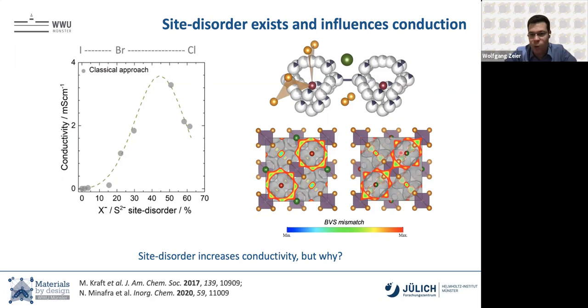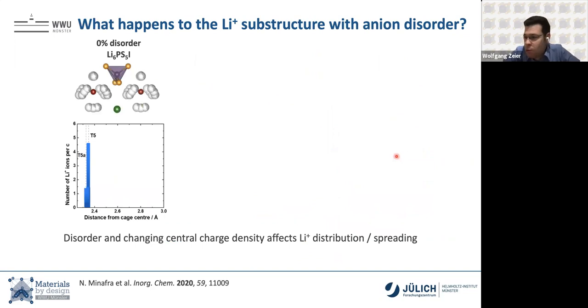And when you turn on this disorder, the cages start connecting and lithium just jumps around in the unit cell. Well, why is the disorder important? To figure this out, we looked carefully at neutron diffraction, temperature dependent, starting from low temperatures to nail down the lithium substructure. And we tried to analyze it from a different perspective, not the typical where are the positions in principle and what are the occupancies.